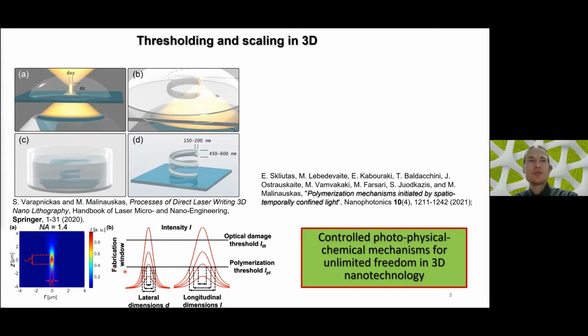And depending on the focusing optics, we can go to diffraction limited dimensions. And by additionally tuning intensity, whether average power or pulse energy, the most defining parameter is light intensity, but we can choose the conditions when both lateral and longitudinal dimensions can be precisely tuned. We need to exceed the polymerization threshold, but not exceed the optical damage threshold. And within that range, we can safely work within the fabrication window, and this additionally allows tuning of feature sizes.